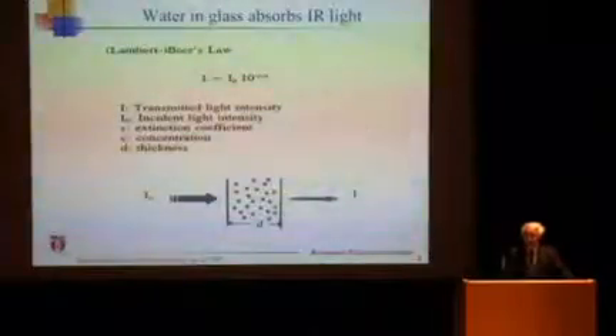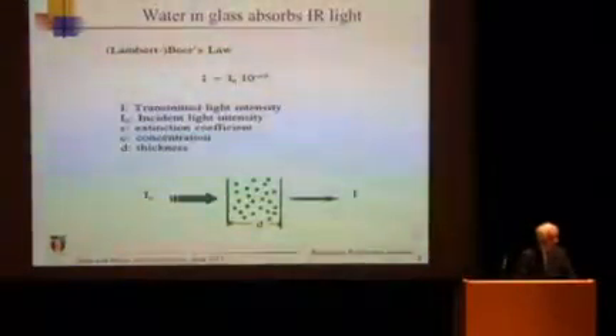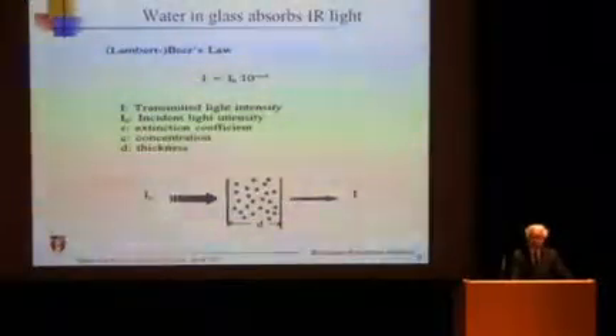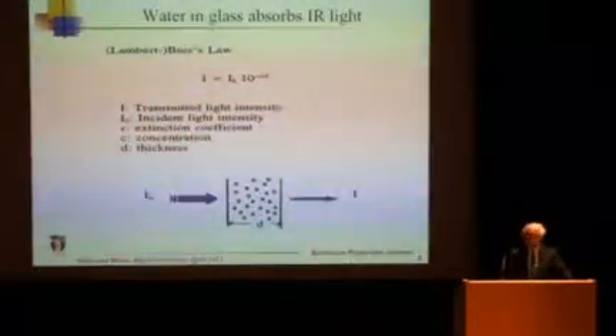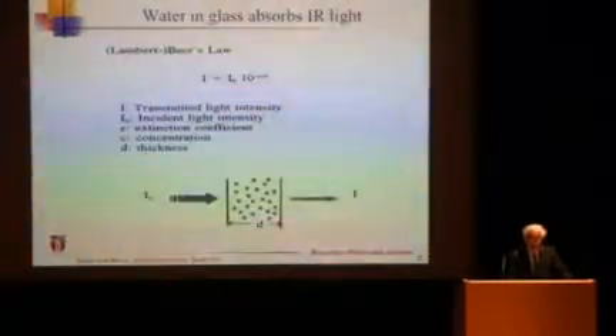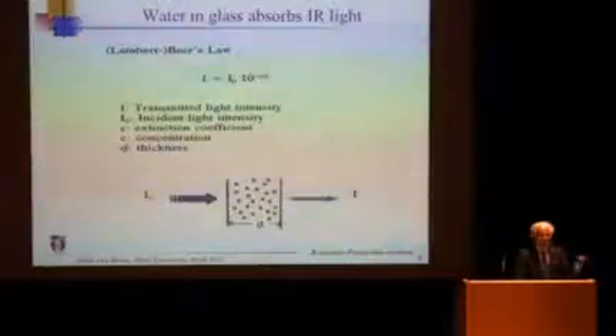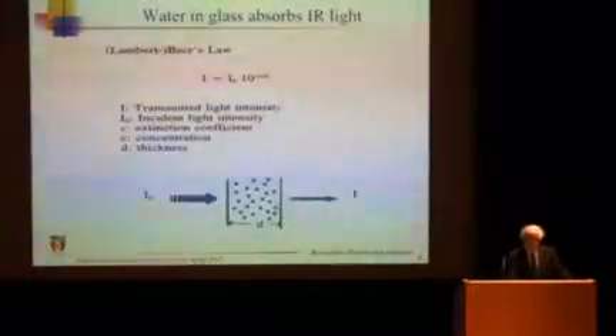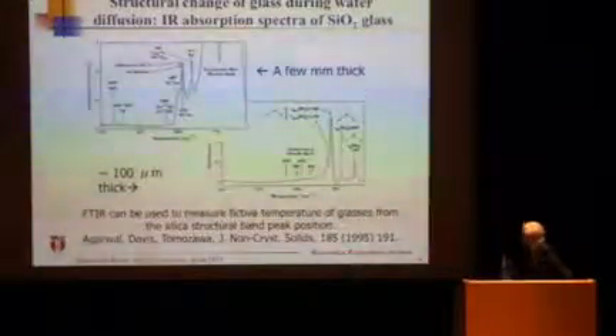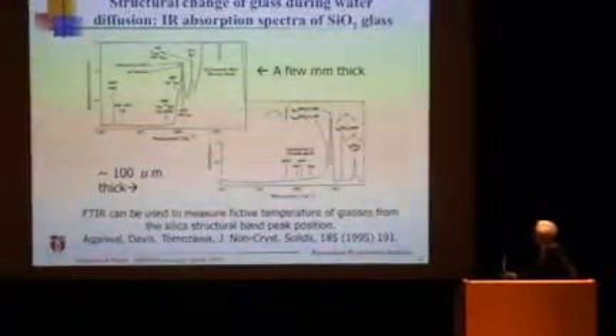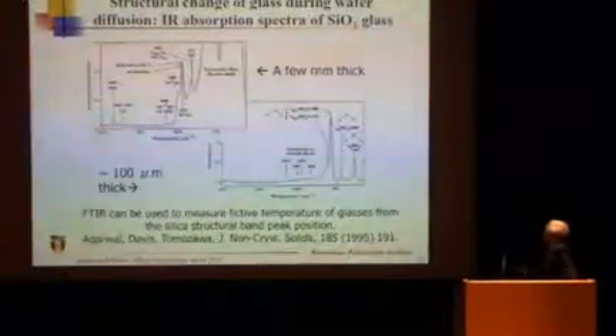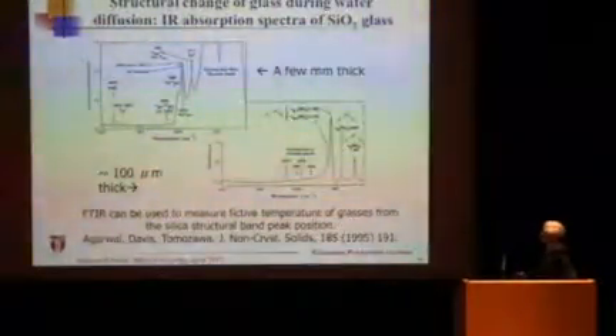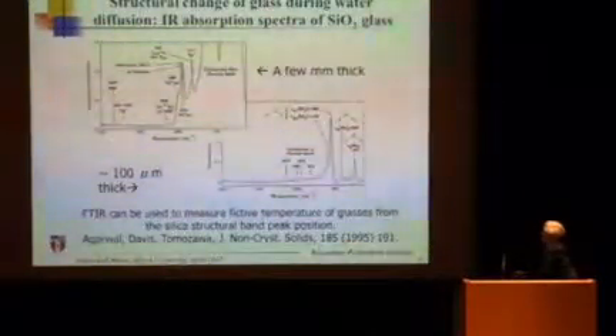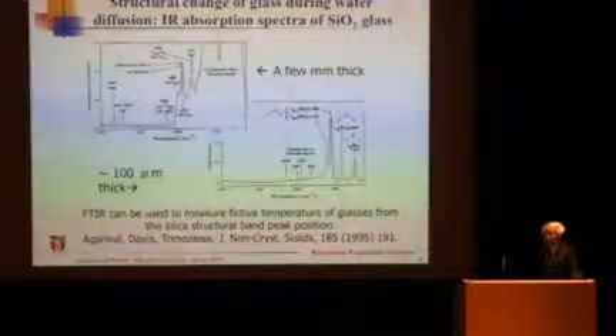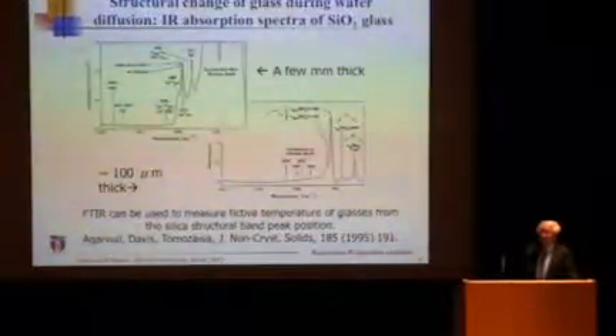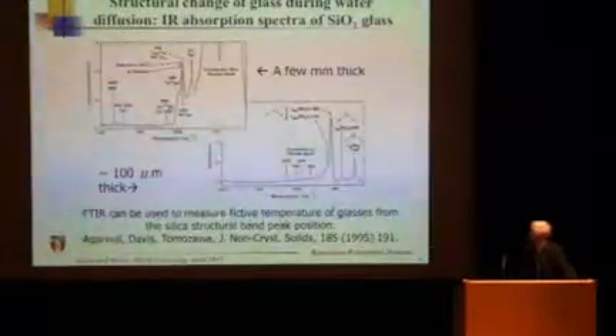Water can be in glass, normally existing as an impurity, and its existence can be detected by infrared spectroscopy, FTIR. When there is a small amount of water in glass, the infrared beam is absorbed, and that can be shown in this slide. This is the FTIR. This one is a little bit thicker specimen, a few millimeters, and this peak absorbance, and this small peak is due to water impurity. And the small amount of water in glass has a dramatic influence on various glass properties.